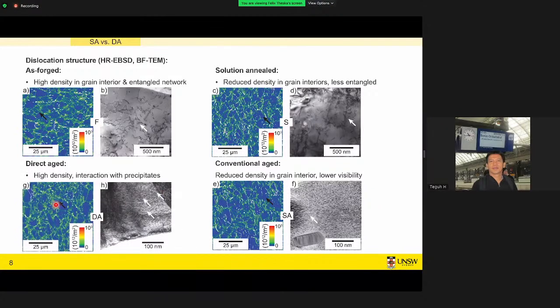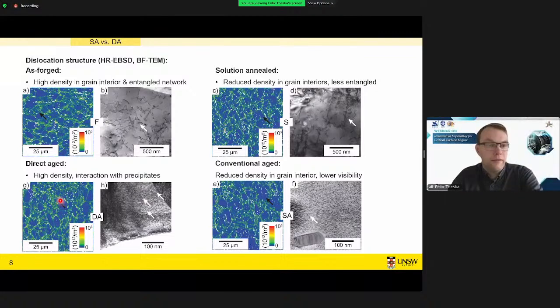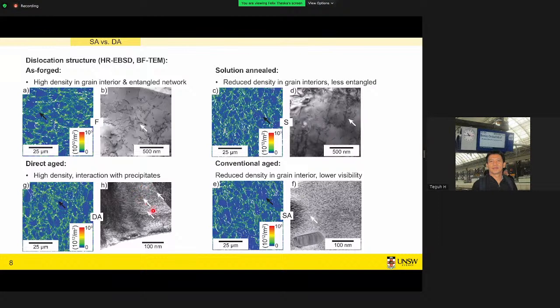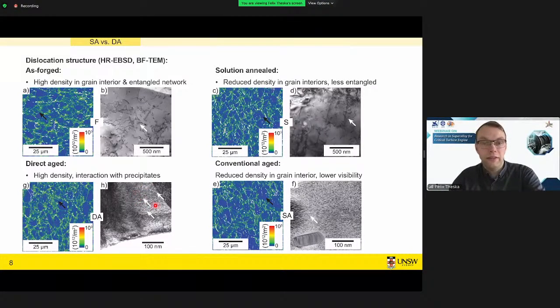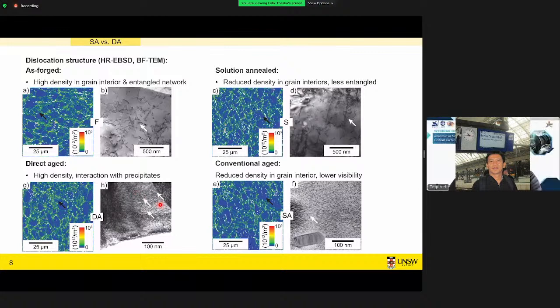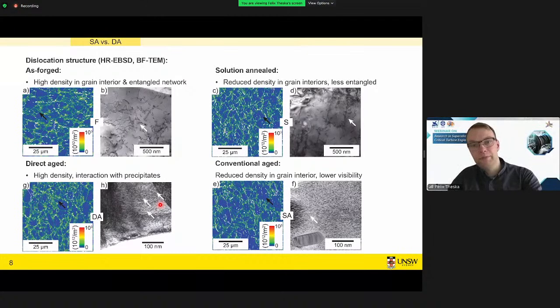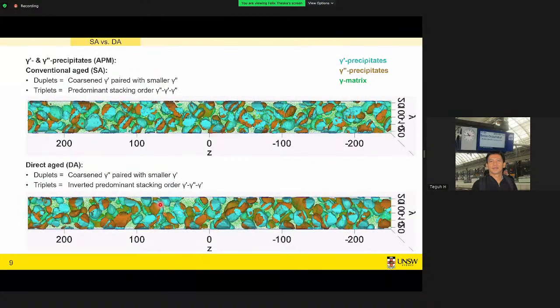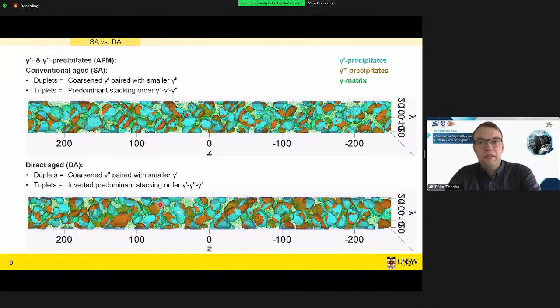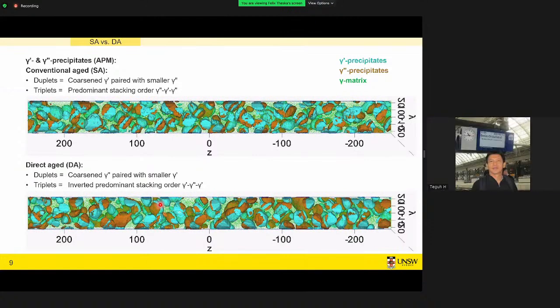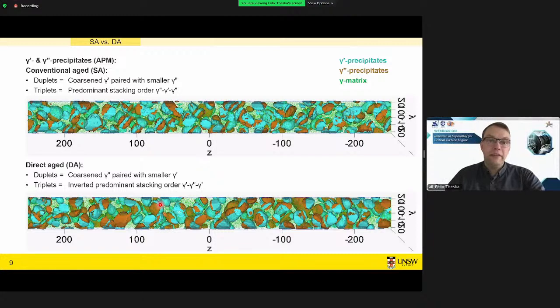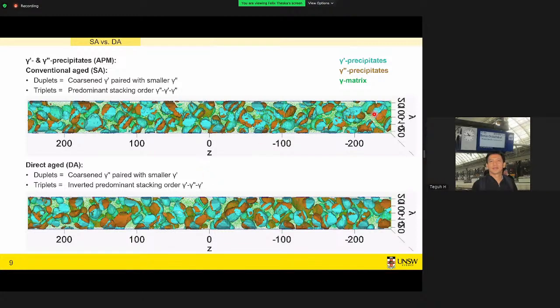Again, in the EBSD map, we find that there are still some dislocation traces remaining in the grain interior, and in the TEM we can see, although there's a lot of precipitation happening, we also see these dislocation structures. So they are far more pronounced, which is in agreement with previous research. What's difficult though with the TEM is to distinguish between these two types of precipitates, gamma prime and gamma double prime. And here the atom probe helps us a great deal because we can separate them based on their individual chemistries.